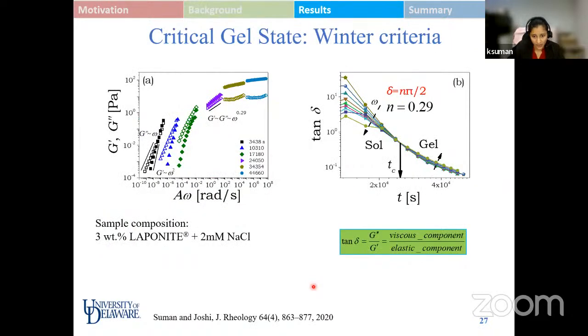So with this system in hand, we first try to characterize the sol to gel transition. As I mentioned previously, it can be very well characterized using the Winter criterion. So we again apply a series of frequency sweeps. The difference between the first system, which was a system of spheres, and this system is that the earlier one was a thermoreversible system, which means that it undergoes transition with respect to temperature, whereas laponite undergoes spontaneous gelation, that is, it undergoes transition with respect to time. So over here, we do multiple frequency sweep experiments at different times during its transition from sol to gel state.